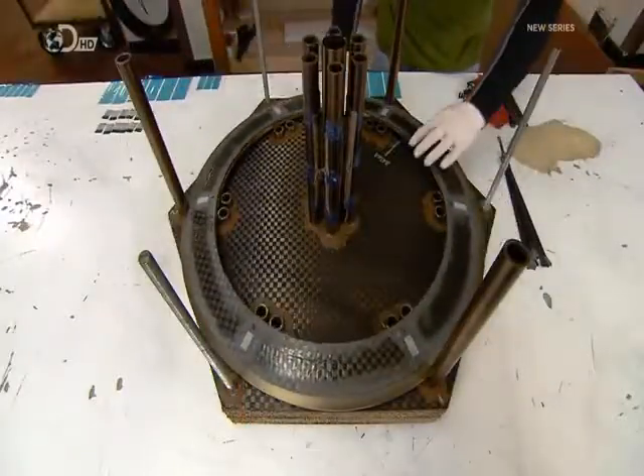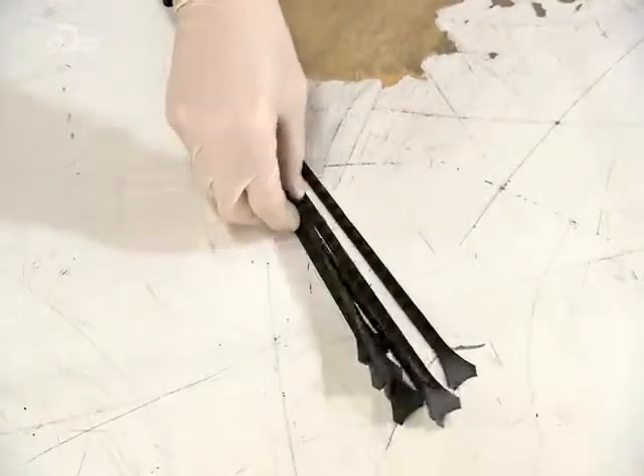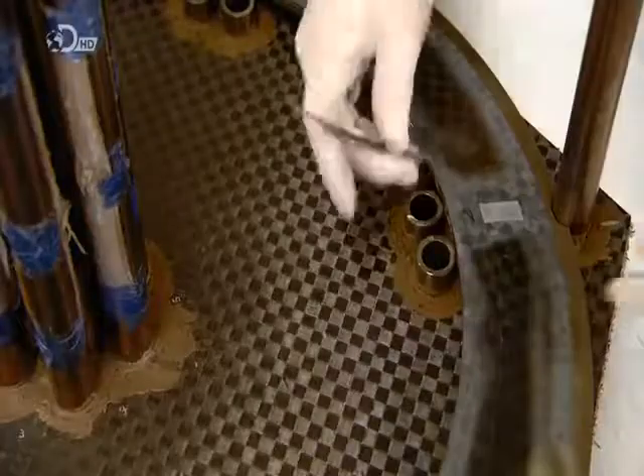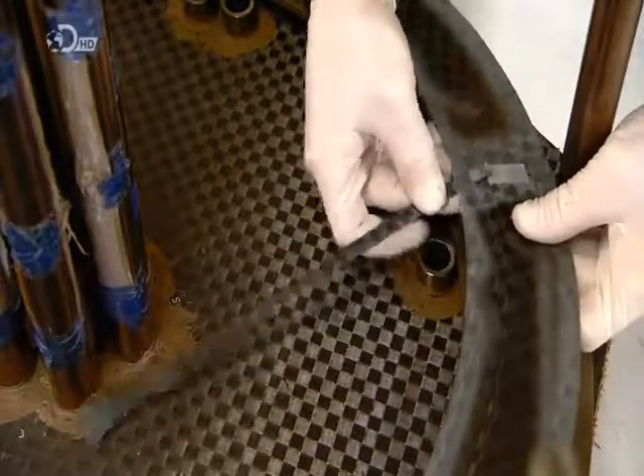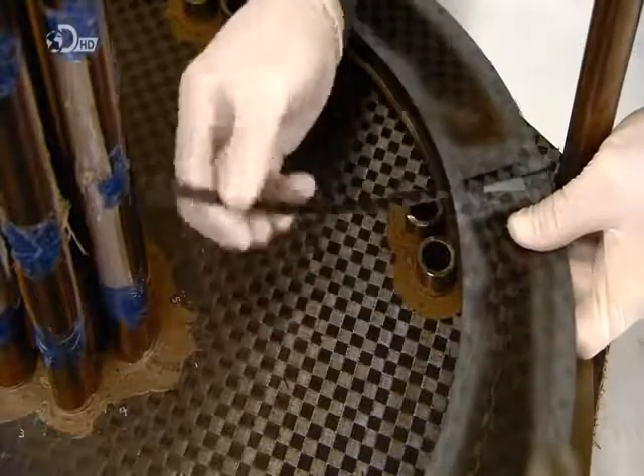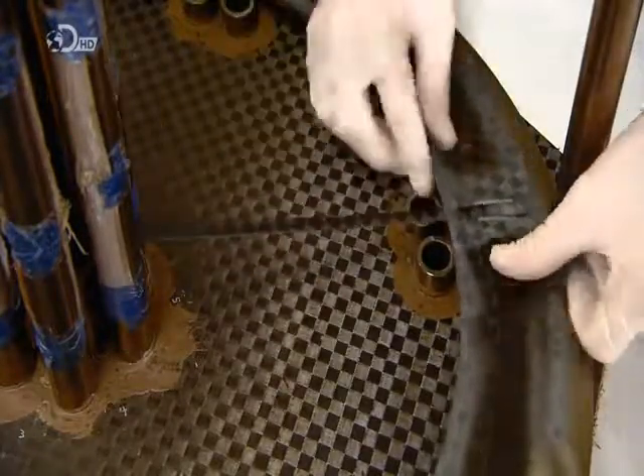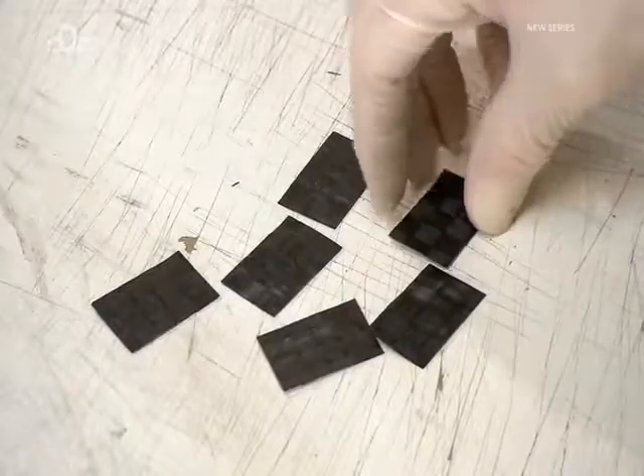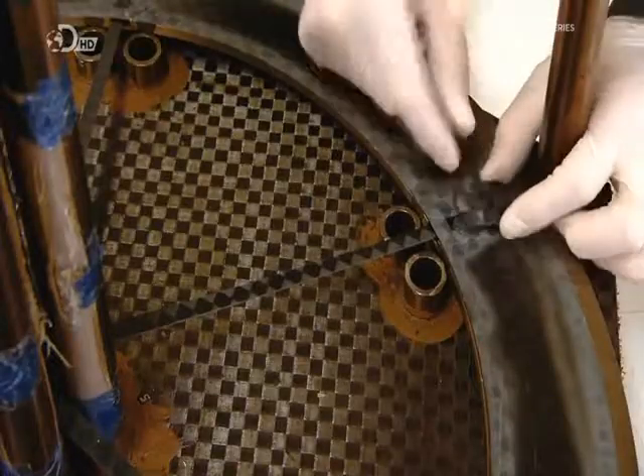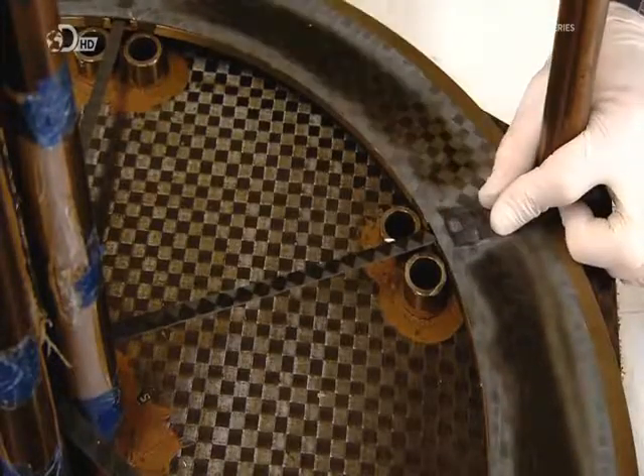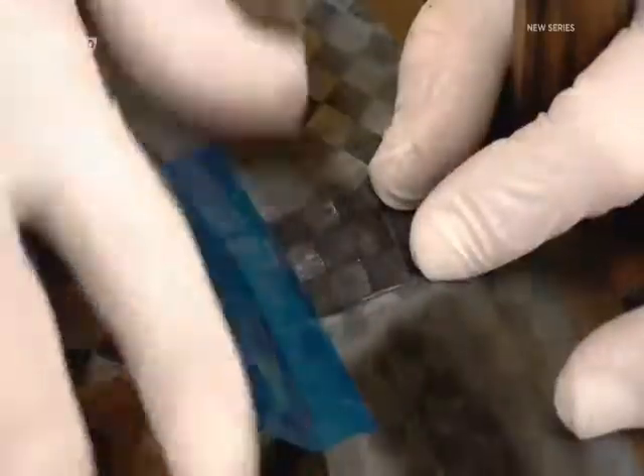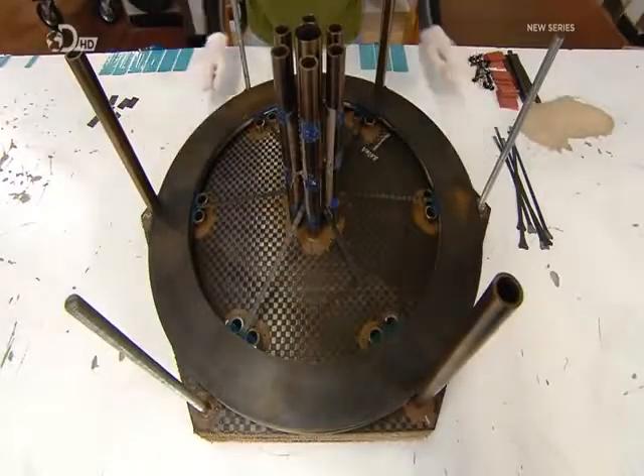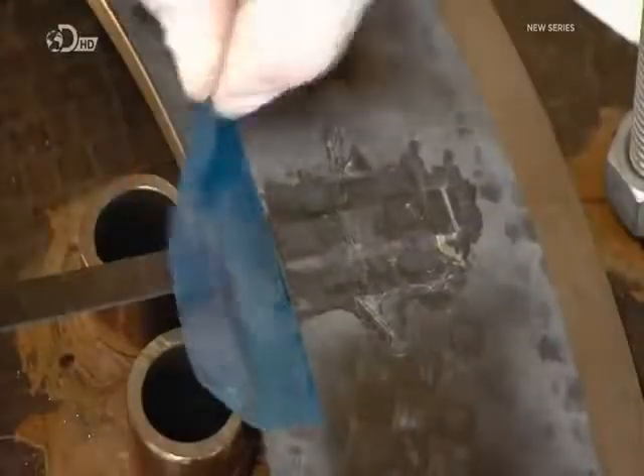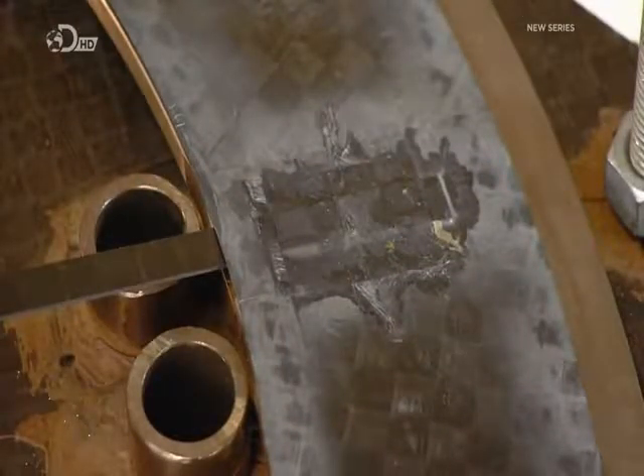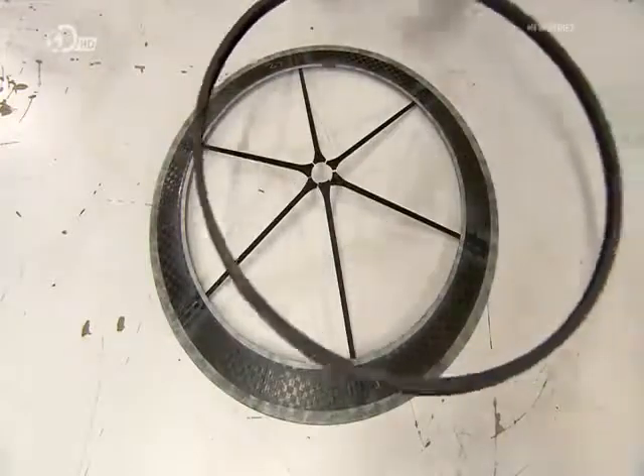Now for wheel assembly. The technician inserts flat carbon fibre spokes into holes in one half of a sidewall. Adhesive and carbon fibre will bond the spokes to the sidewall. A carbon fibre patch is put where the end of the spoke meets the sidewall, and it's taped there. With all the spokes in position, he lowers the lid and applies mechanical pressure. The spokes bond to the sidewall, and it's ready for the rim.